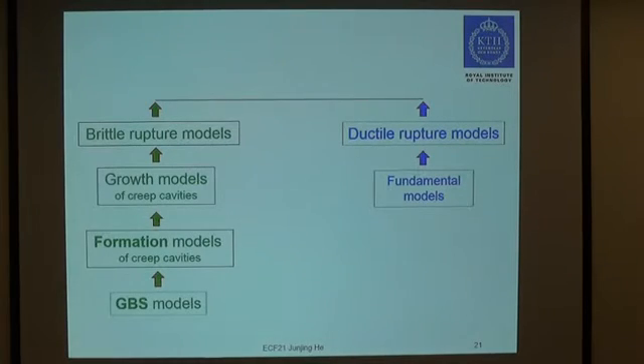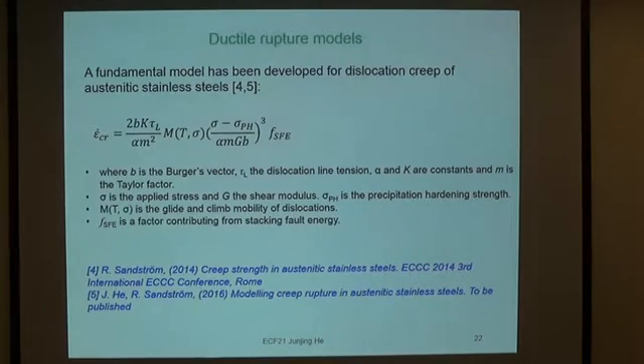But on the other hand, there is also the ductile rupture behavior, where the fundamental models have been used. And here is the fundamental model that has been well developed for dislocation creep of austenitic stainless steels. It's related to the glide and climb of dislocations and precipitation hardening and the stacking fault energy. I will skip the details here because it's a well-established model and also available in many of our published papers.